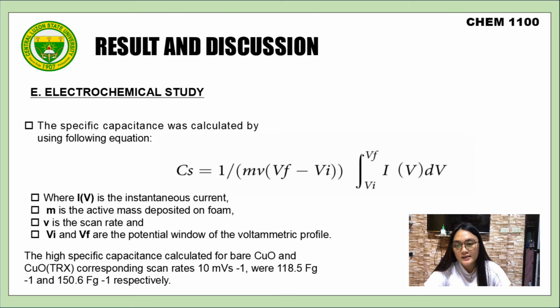The specific capacitance was calculated by using the following equation, where I(V) is the instantaneous current, m is the active mass deposited on the foam, v is the scan rate, and Vi and Vf are the potential window of the voltammetric profile. The highest specific capacitance calculated for bare copper oxide and copper oxide TRX at a scan rate of 10 mV/s were 118.5 F/g and 150.6 F/g respectively.